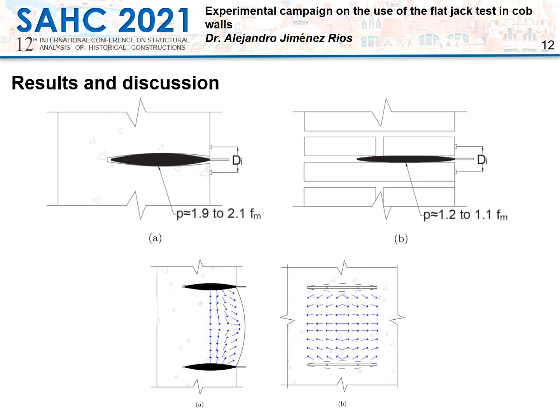Furthermore, the almost zero deformation of the flat jacks along their edges, namely at the wallet's faces, does not cause any restriction to the bulging of the material, as can be seen in Part A of this schematic figure. Therefore, bulging compensates some of the vertical deformation caused by the increment of the pressure, while at the same time contributing to the further increment of the horizontal deformation of the material caused by Poisson's effect, as depicted in Part B of this figure.